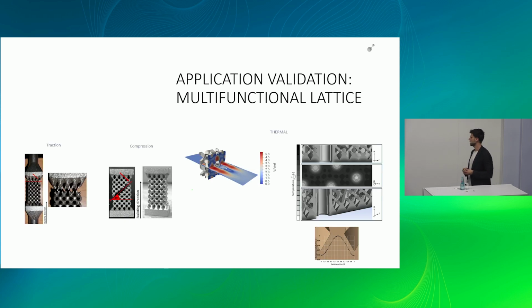For validation, it was actually a very quick one. We just printed some samples for traction and compression. That means we took the actual lattice geometry, so the original beam thickness and the distribution, and we put it to tensile testing. So first traction and then compression, so pushing and pulling, and took some values there. For thermal, we took a representative sample of these lattice structures and checked for turbulence and for velocities compared to reference velocity. And what we detected, and that can be seen in this picture, is that we have a heat buildup in the center of the cones.